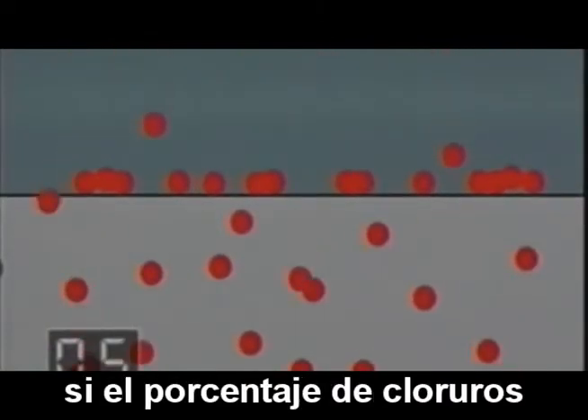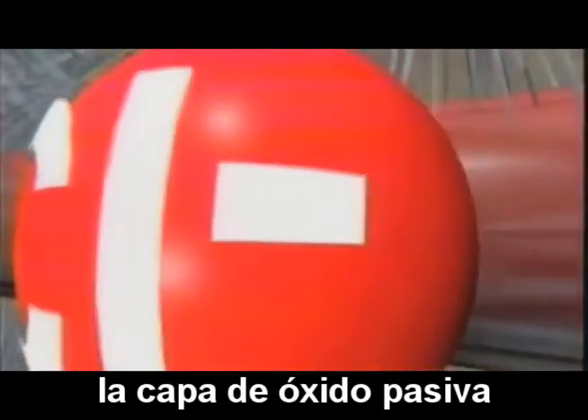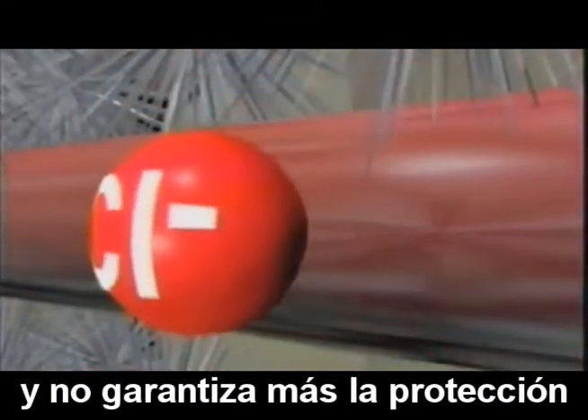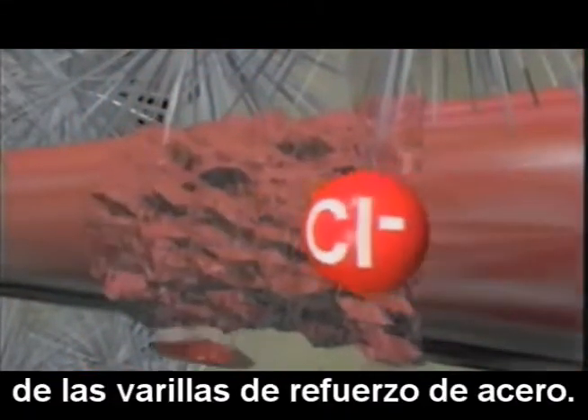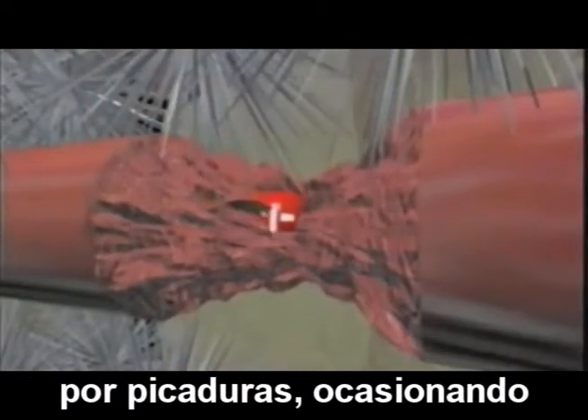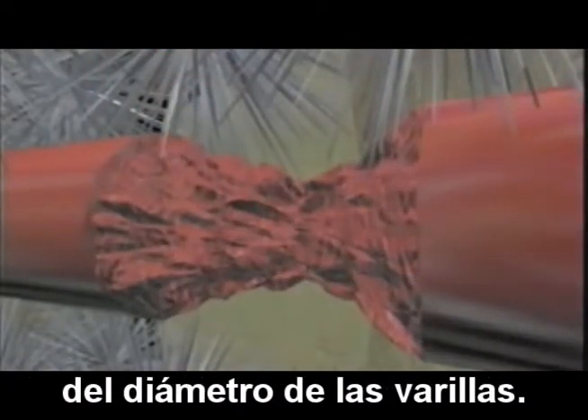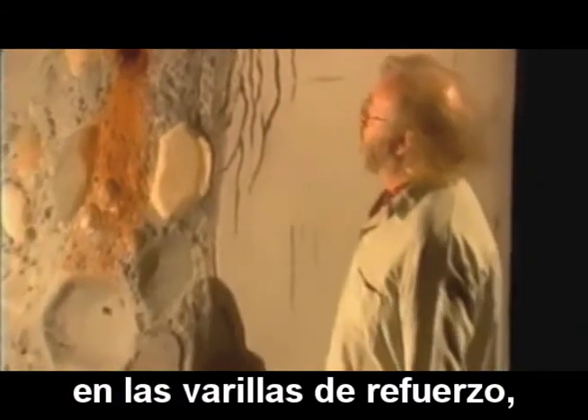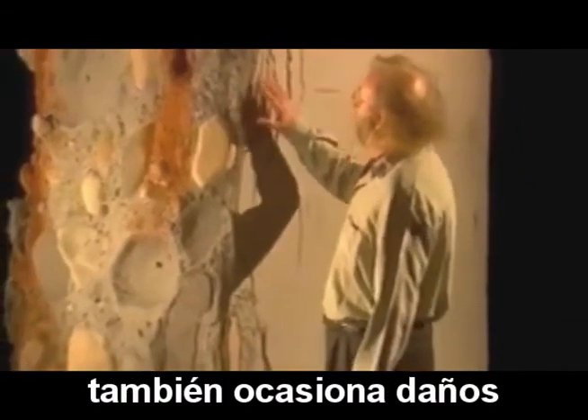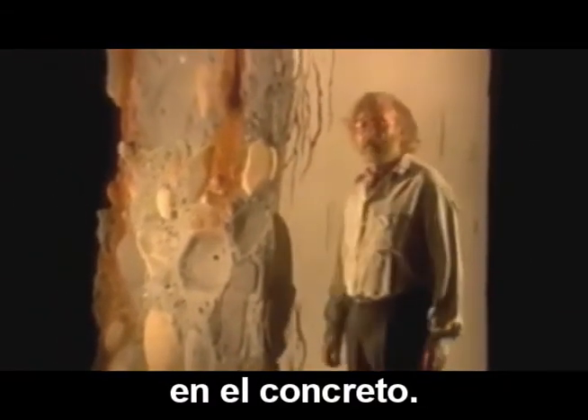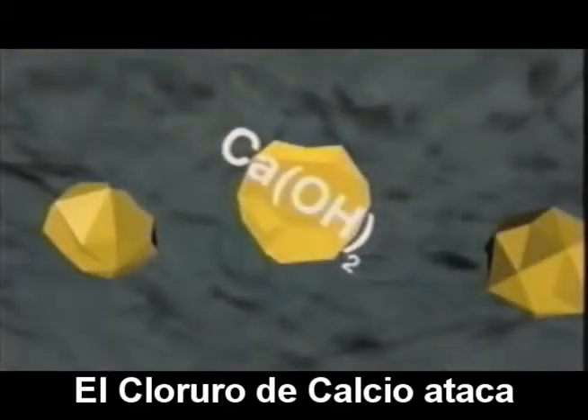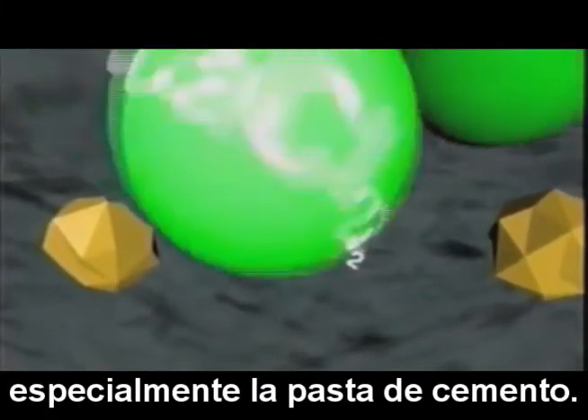If, however, the percentage of chlorides increases, the rust layer becomes porous and no longer guarantees any protection to the steel reinforcing bars. The metal undergoes localized pitting corrosion, which dangerously reduces its diameter. Apart from the corrosive action on the steel rebars, these salts can also damage the concrete. Calcium chloride especially attacks the cement paste.